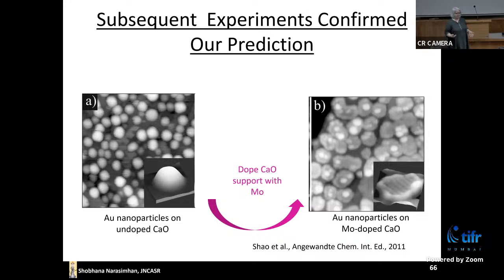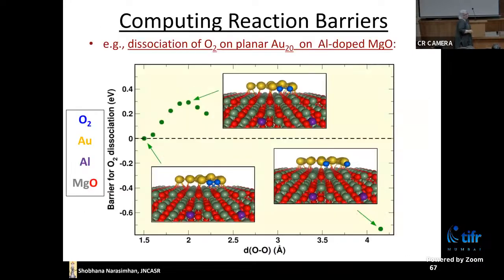Now, just to temper it with some negative stuff, we also predicted that it would be a very good catalyst, because that's why we were doing it. Okay, so this is again from density functional theory. What we're doing here is on this flat gold nanoparticle, we are putting in blue here an oxygen molecule, and we're stretching the molecule till it breaks. So we're dissociating the oxygen.